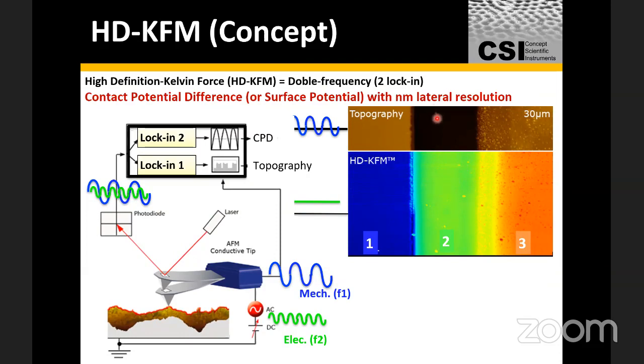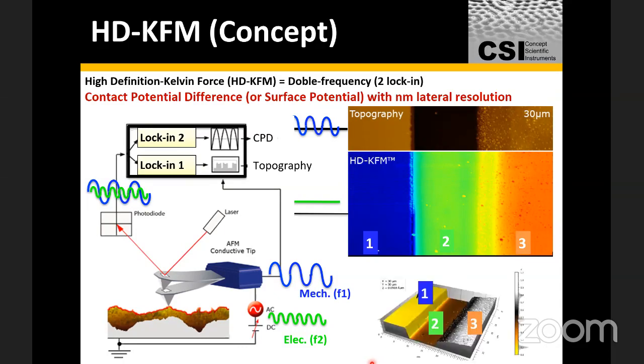In fact, in the topography we cannot really capture some of the dirt, but the surface potential signal is so clean that we can actually identify some of the dirt on this wafer that doesn't appear on the topography scan. That's really nice to see, because it tells us that we are able to make electronic measurements on surfaces sometimes at a much better resolution than just measuring the intrinsic topography of the surface. I guess I should have brought that up before. That's just a 3D rendering of what the surface is like.